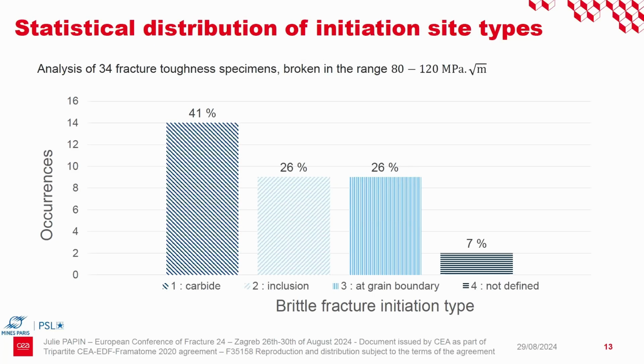So we analyzed 34 fracture toughness specimens broken around 100 MPa square root meter, and here is the frequency of initiation site types. So we have a predominant initiation on the carbide at grain boundary, then a quarter of initiation on inclusion, a quarter at grain boundary with no visible particle, and a few cases that we cannot define because the initiation sites were destroyed or not accessible.